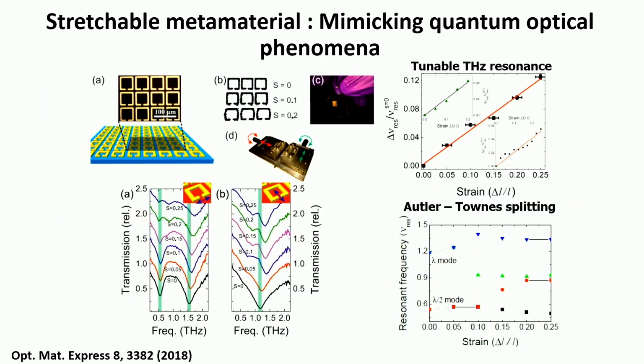Right. So this is another example where we have designed and demonstrated stretchable metamaterials. Here we showed mimicking of quantum optical phenomena, for example. This is on top of PDMS, with gold patterns forming split ring resonators. The idea here is that when you physically stretch, these split rings get deformed. When you deform this and look at the transmission spectra, you see that both the lambda by 2 and lambda modes split up. So this is similar to the Autler-Townes splitting in the quantum domain, but we can mimic those things and look at different applications of these. Right.